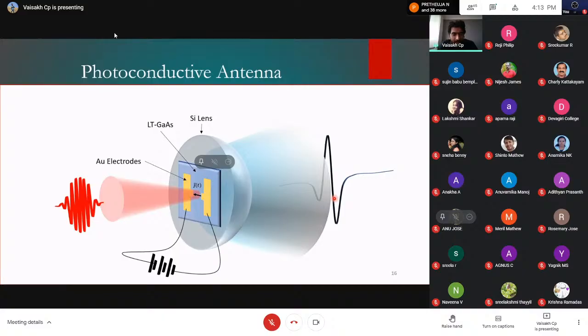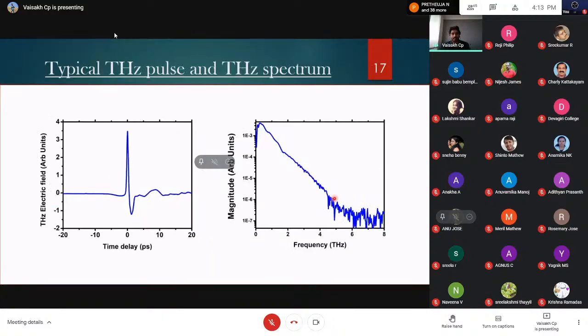So in a pulsed terahertz spectroscopy system, what we directly measure is the electric field. Compared to almost all other spectroscopic methods, like infrared or visible, we measure the intensity more. But here, it's a direct measurement of the electric field, which preserves the phase information. And what we see on the right is the spectrum.